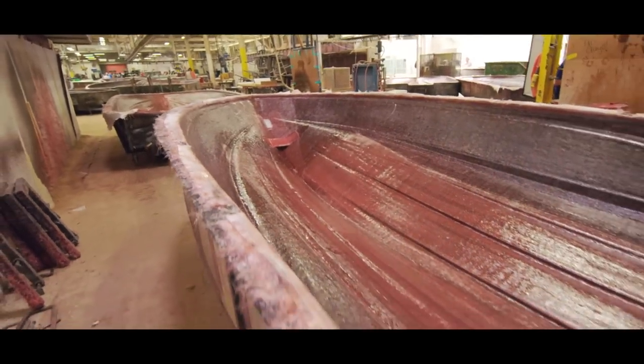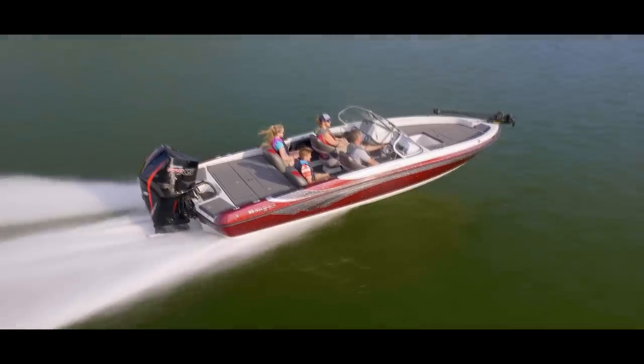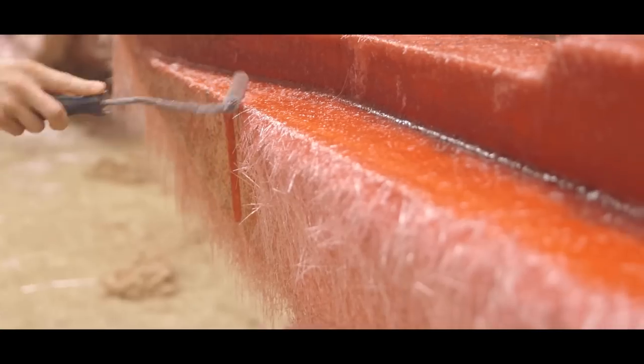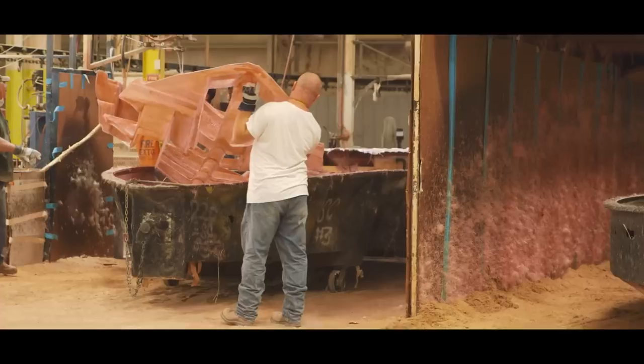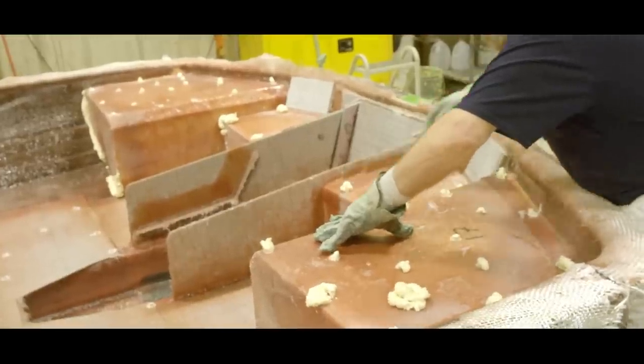The hull is starting to resemble a boat, so let's take a closer look at what makes the inside of a Ranger so special and how we deliver that signature one-piece feel. Beginning at the back of the boat is what is called the Pultruded Fiberglass Transom. After that, the stringers are added. These stringers are made of 100% fiberglass, so there's no wood to rot and no mystery composites anywhere. What you can't see inside the stringers is the injected closed-cell flotation foam in every available cubic inch — leaving no gaps, spaces, or holes, which is the first step in delivering that famous Ranger one-piece feel.